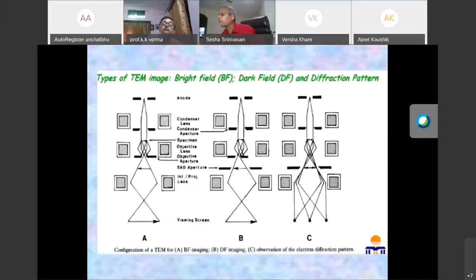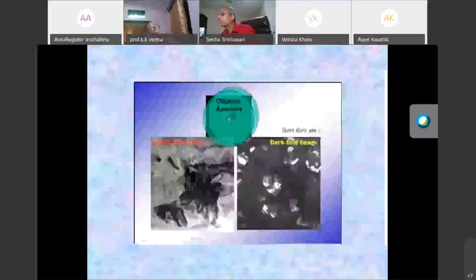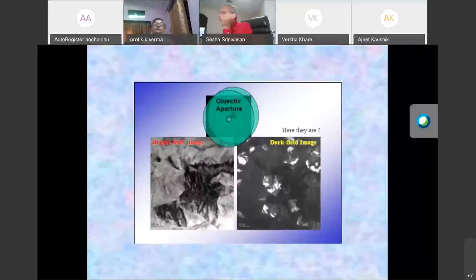TEM can also work in bright field mode and dark field mode, and this will give different information. Dark field and bright field have their own advantages, and people can work in dark field or bright field. Depending on the material contrast, the Z number, atomic number, if you have a combination of two materials and you want to do the TEM by this contrast, you can know exactly which area is the low Z and which area is the high Z. And these are the bright field and dark field images on your screen, which suggest this information.